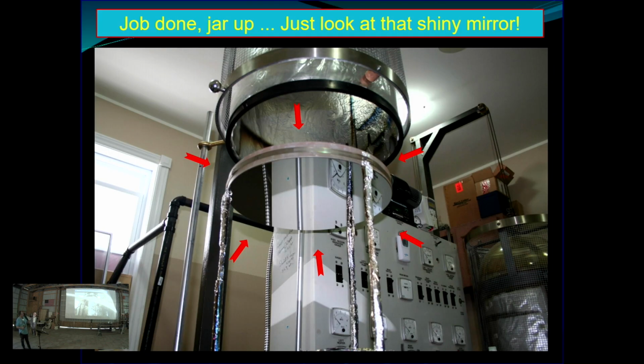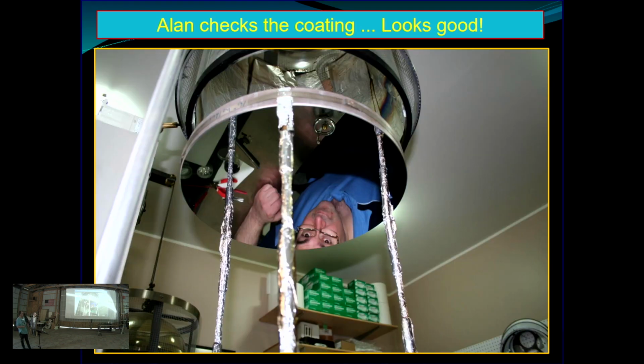So that's what a 16-inch mirror looks like when it's done. Now, you probably ask yourself, how do I know how thick the coating is and everything else? Well, we use interference. When you're applying the coatings, the aluminum is done in a second. You just blast it away and it goes on. The other coatings, you can have control over because it can take several minutes to do the magnesium fluoride and several minutes to do the cerium dioxide. You can take as long as you want, actually.